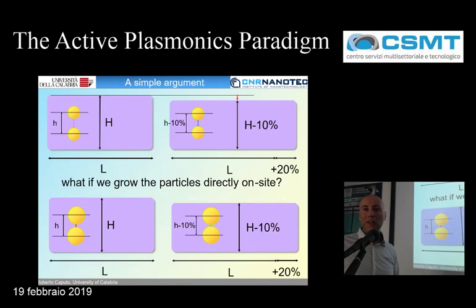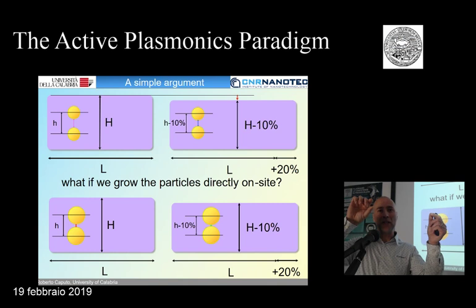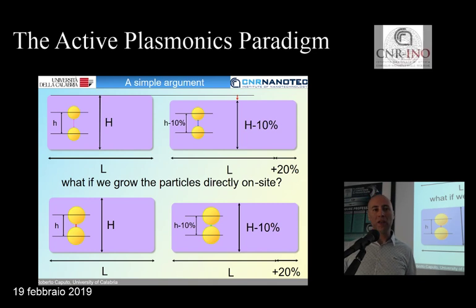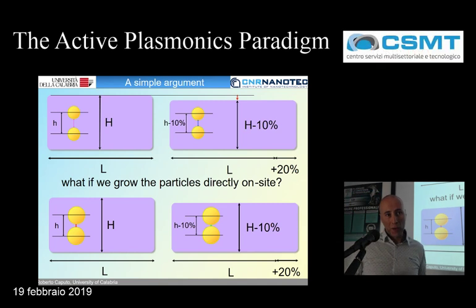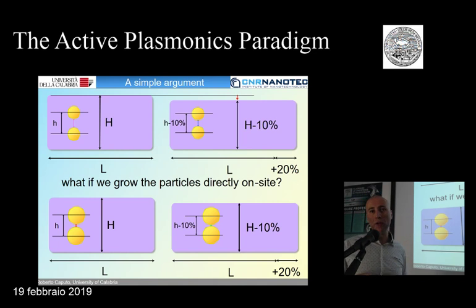So if you have a flexible substrate and you elongate it in one direction, you tend to decrease the size in the direction orthogonal to the elongation. If you have an elastic material with a Poisson coefficient of 0.5, in principle, if you elongate by 10 in one direction, you will compress by 5 in the perpendicular direction. So what really happens is that all the particles along the direction perpendicular to elongation tend to go close to each other.